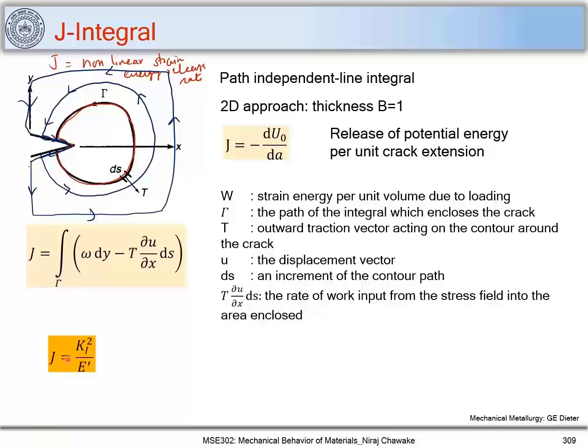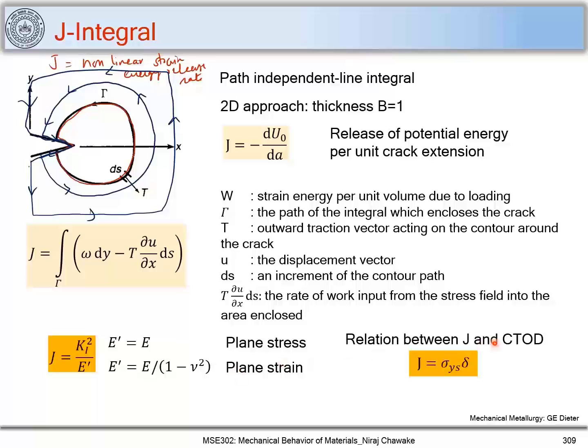So we can find out the value of J to be equal to K1 square upon E dash, where E dash is nothing but E, which is the Young's modulus, when we consider a plane stress condition. E dash is equal to E upon 1 minus mu square in the plane strain condition. So what is the relation between J and crack tip opening displacement? You can find that J is equal to sigma ys into delta.